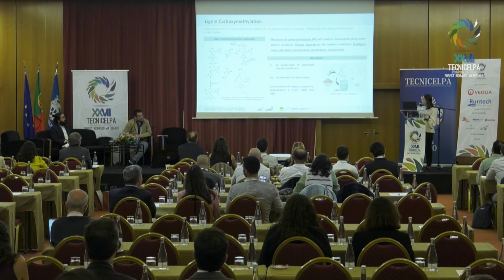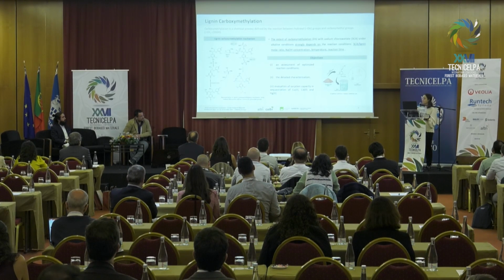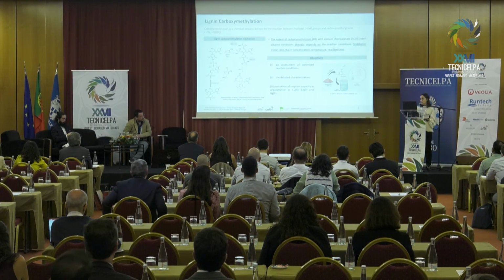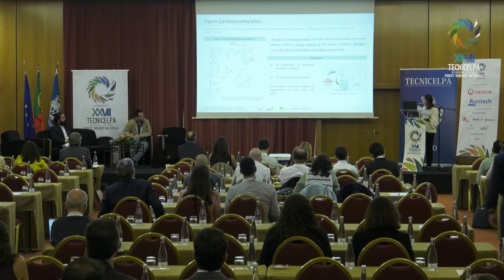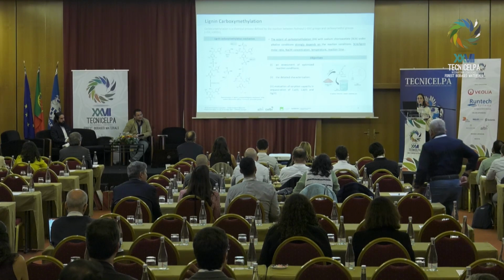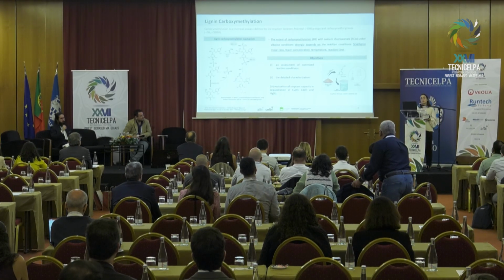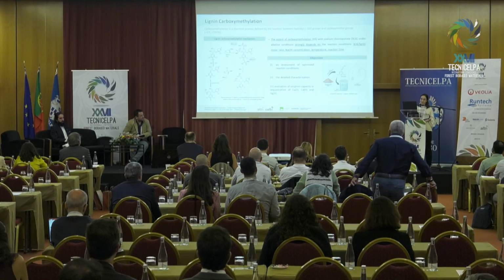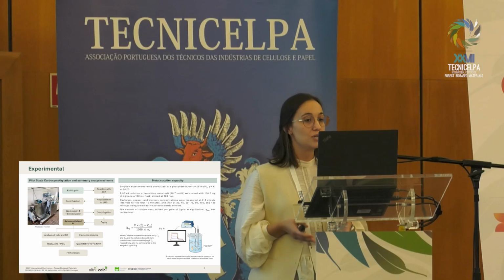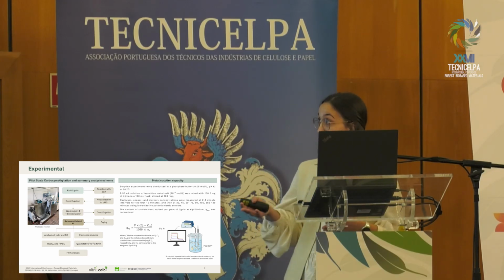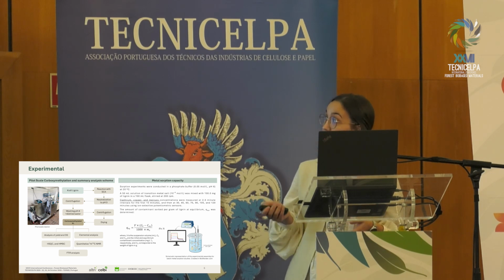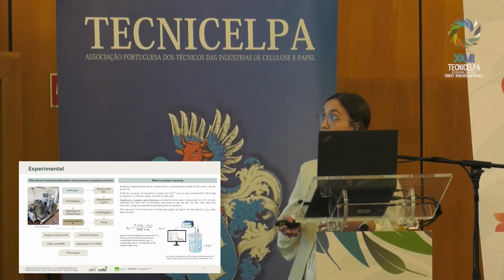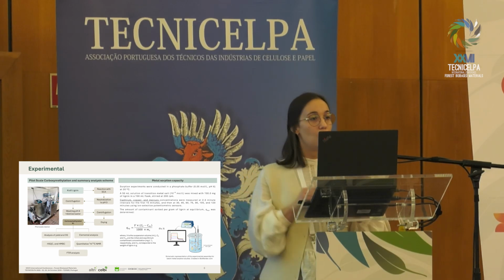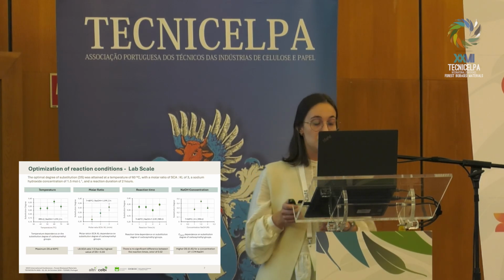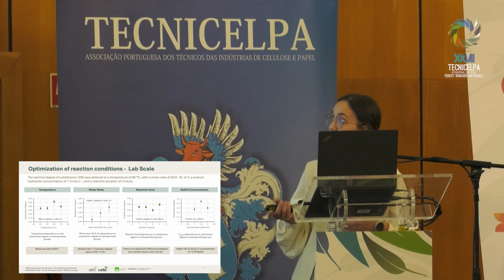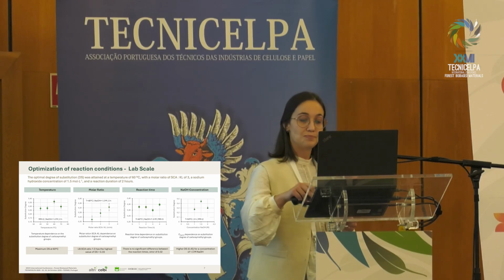Also, during this reaction, sodium chloride and glycolic acid are formed as byproducts. This reaction strongly depends on the sodium chloroacetate to lignin molar ratio, the sodium hydroxide concentration, the temperature, and the reaction time. The main goal of this work was to assess the optimized conditions for this carboxymethylation, to have a detailed characterization of the modified lignin, as well as the substitution patterns of these new carboxymethyl groups, and to assess the ion exchange capacity towards transition metals.